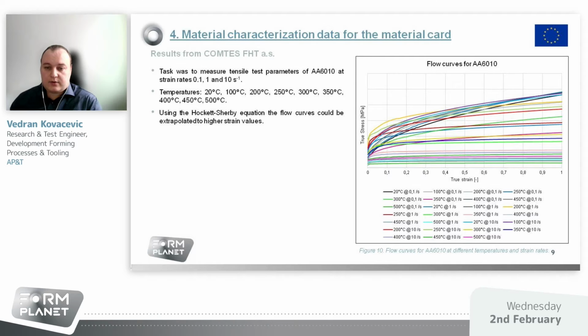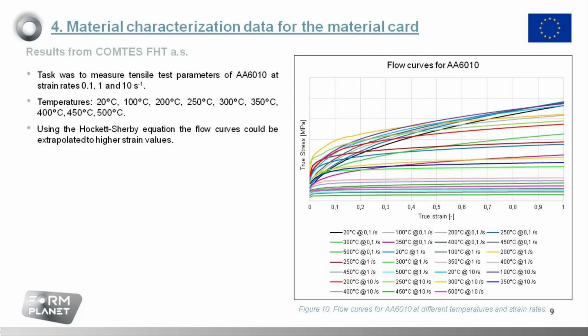COMTES FHT had a different experimental approach for the hot tensile tests. They performed the tests on the 6000 alloy. The main difference being that the hot tensile tests were conducted at different strain rates and at a wider temperature range than the tests from Fraunhofer. In addition, they used a different method of heating up and cooling down the samples during the experiment.